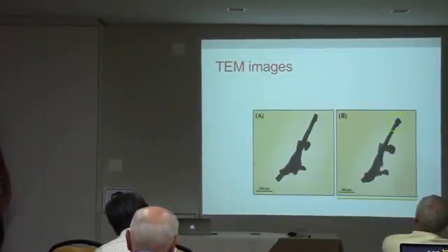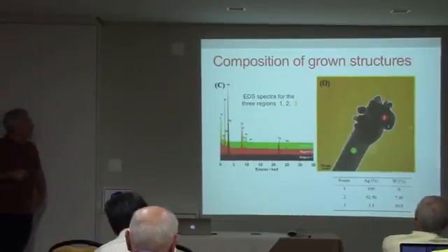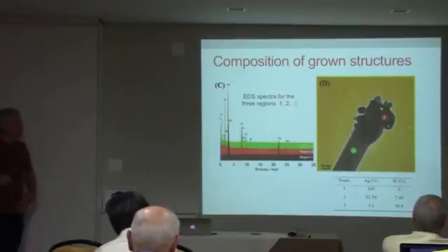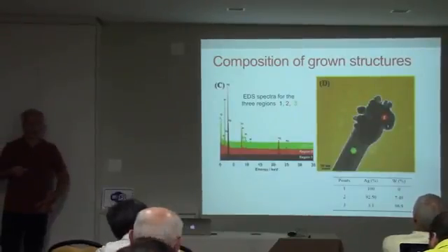What is the origin of this structure? This is again another silver tungstate, and after a time, we see this bit. When we analyze the composition, we find that it is mainly made of silver, metallic silver.